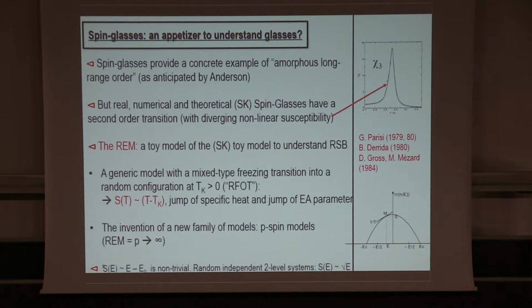And of course, in the paper by Bernard, there's also this amazing invention of a new family of models. He explained yesterday, the p-spin models, which I think open the path to many, many things that we are all doing now. The REM is just the limit when p goes to infinity of that. So this is the graph of the log of the number of states in the random energy model, and you see that it goes to 0 linearly close to the ground state. And actually, that's not so trivial. If you throw at random two-level systems, then you won't get this linear vanishing. Actually, you'll get square root behavior. So it seems that this thing requires some kind of strong interaction between individual elements.